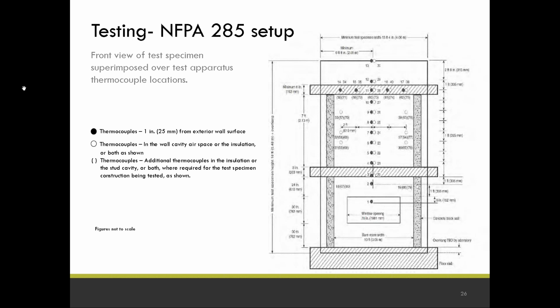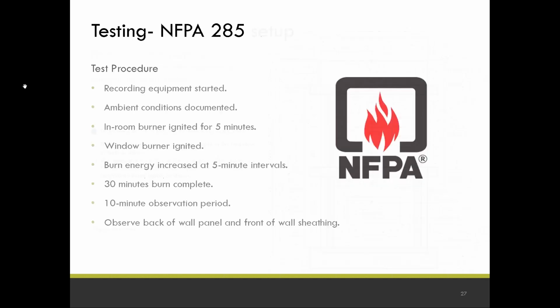5 minutes later, they start another fire at a burner right at the bottom of the top jamb of the window. And then every 5 minutes thereafter, they increase the heat up until 30 minutes, it's all shut down, and you determine, well, by then you know whether you passed or not, but you determine what the end is.